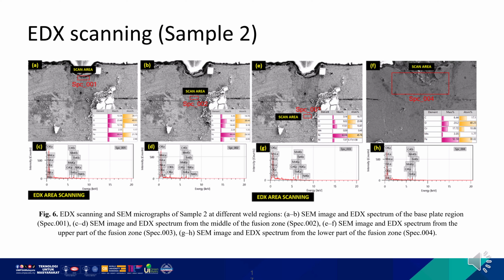So in sample 2, EDS analysis reveals significant oxidation, with oxygen concentration peaking in the fusion zone while absent in the base plate. Iron dominates at 47.56%, but chromium depletion and nickel loss confirm severe oxidation during the welding process. Why does nickel loss matter? Nickel oxidation degrades the corrosion resistance of SS304, and this can be mitigated by employing shielding gas such as argon or other gas to suppress oxygen ingress.